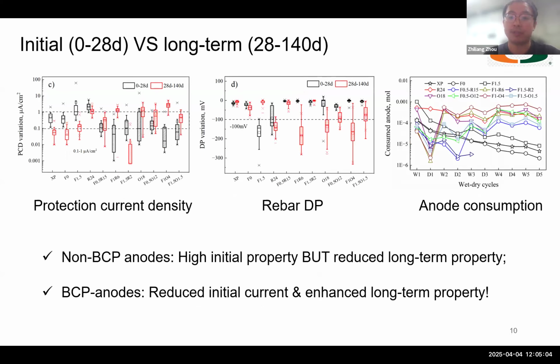It can be observed that the sacrificial anodes without biochar addition had higher initial property, but decreased long-term performance. And differently, with the biochar addition, the sacrificial anodes have a limited initial property, but their long-term performance is significantly enhanced. And this research confirmed our hypothesis. This is because the biochar can absorb a lot of electrolytes at the initial time, so it decreases the pH value of outside matrix. However, over a long time, the absorbed electrolytes can come out to increase the pH value of the external environment. So the anode's activity is enhanced during the long term.